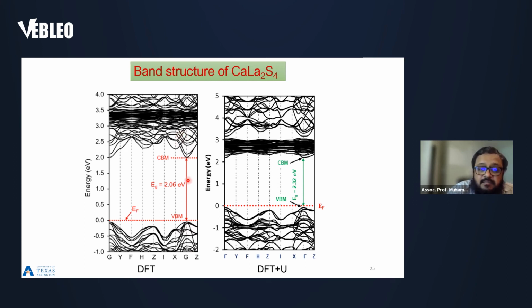What it does is push these bands above, as you can see, but we couldn't add a U value on the lanthanum 4f orbitals because those are unoccupied. The DFT plus U method doesn't work on unoccupied electrons, hence they remain at almost the same position. What it does, it gets decoupled.